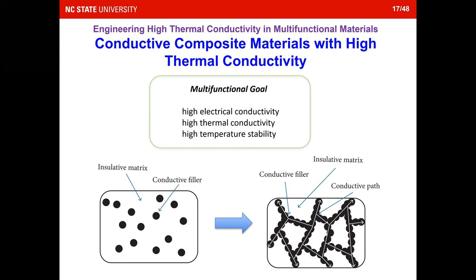So here's the first example we have. We have a multifunctional goal: in this application scenario, we want high electrical conductivity, high thermal conductivity, and high temperature stability. We want a material that can work at high temperature, and at the same time have high electrical conductivity and thermal conductivity. So we think about composite materials and putting in conductive fillers, right? That's the easy way to get high electrical and thermal conductivity. But if those fillers are not connected, they're just isolated islands, it's not easy to make them very high thermal conductivity. And what you get is just a volumetric average.